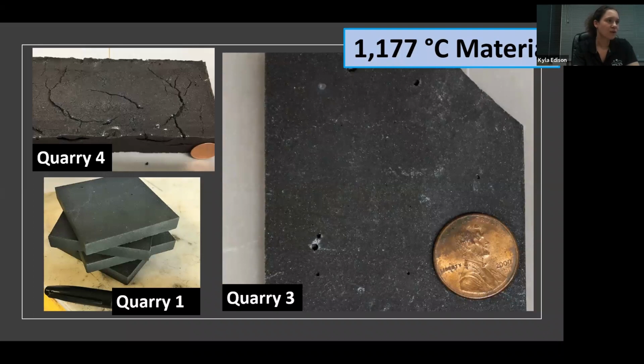And Quarry 4 is very cracked and still isn't doing very well with sintering. Basically what we ended up doing is with the lower temperature material, we were sintering, bringing that stuff up to temperature, letting it hold for a certain amount of time, and then just letting it cool naturally.